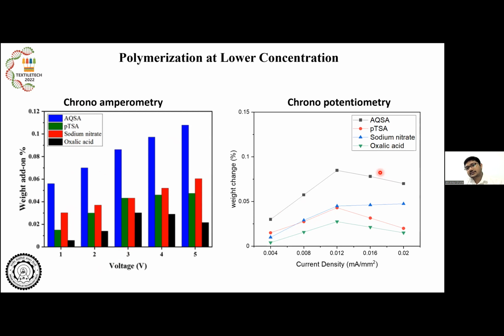In the other figure, chronopotentiometry, when constant current was applied for polymer formation, again the weight goes on increasing, but after a certain current density, these chemicals start ionizing and they decompose and do not participate in the reaction further. So, being the more stable system, this chronoamperometry process was used and constant voltage was applied.